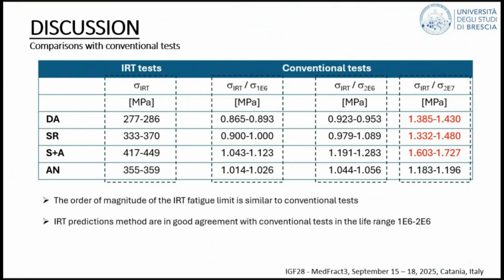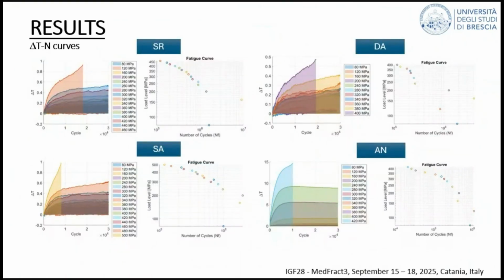And the other possible explanation is instead that we are facing a material in which we have defects inside. So it may happen that the fatigue is triggered by a defect which is not activating some mechanism that generates heat on the surface. So you don't get on the surface any advice that something is happening, because fatigue is propagating from an inner defect. And essentially, we've got the same type of interpretation for this result.